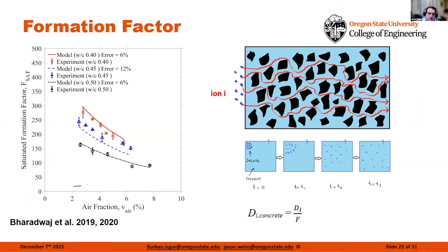And that error is these air voids all of a sudden start to become conductive. But even with this error, we're able to predict this very well based on first principles. So the model prediction here is not a curve fit. It's not anything like that. It's really saying, I started off with these chemistries. I've now predicted the porosity and I've predicted how connected these pores are. And all of a sudden, I can now predict how fast ions are going to be moving through the concrete.